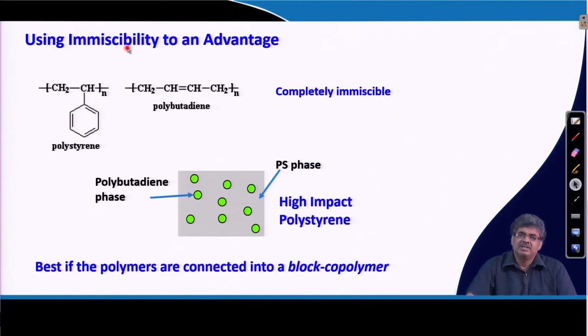Now, we can use this immiscibility to our advantage. For example, polystyrene is a brittle polymer. Now, to improve the impact behavior or ductility of polystyrene, this rubber, polybutadiene rubber, is added. Now, if they were completely miscible, then we would have a single phase, and the impact property of polystyrene would have increased marginally because of the presence of polybutadiene. But because they are immiscible, we can have polybutadiene added in the polystyrene matrix, and as a result, this polybutadiene will phase separate and remain as this type of phase separated domain,